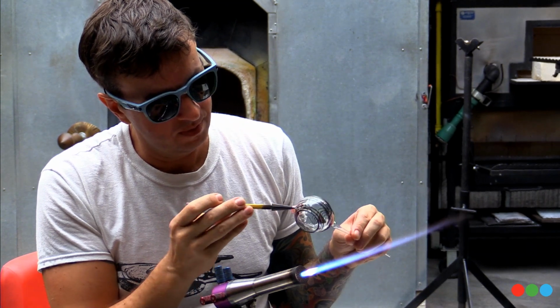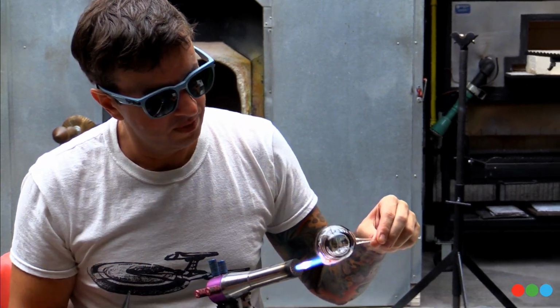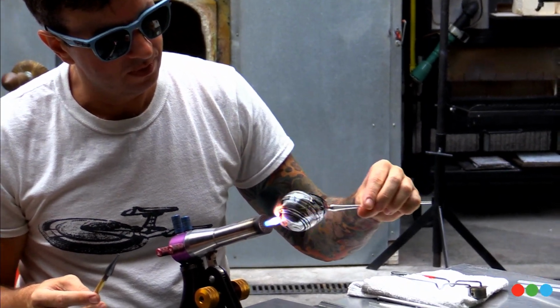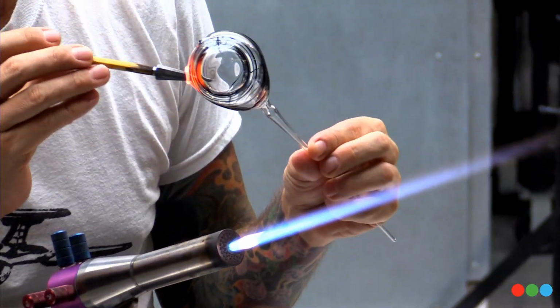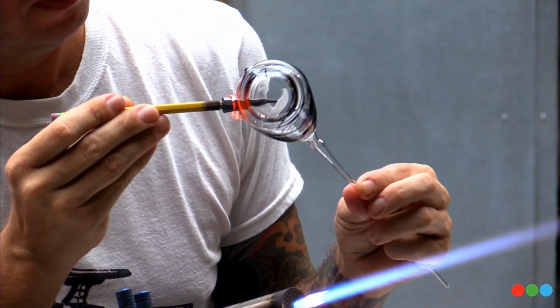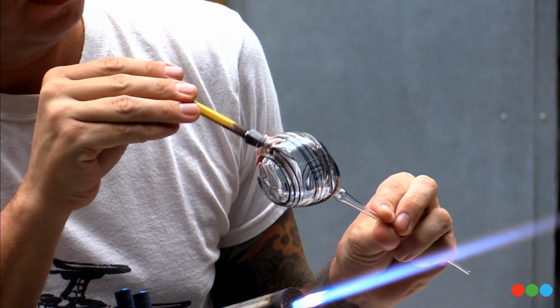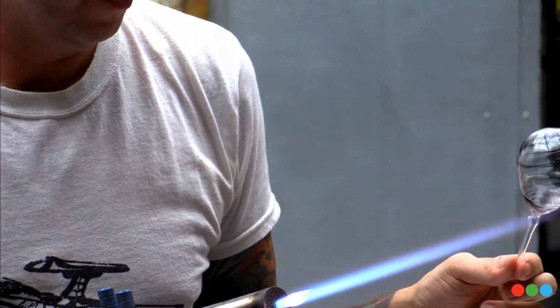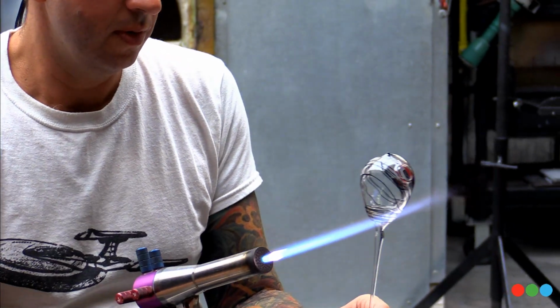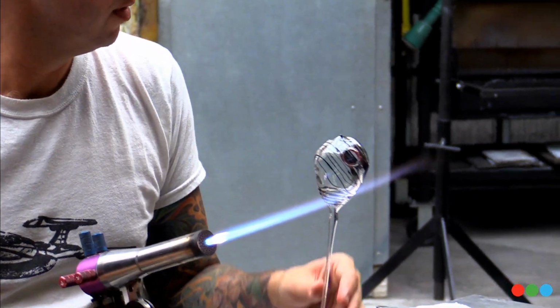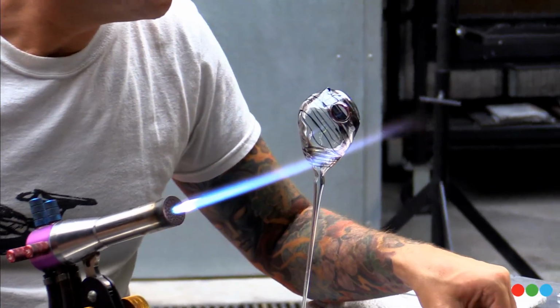It actually grows. It's not a lot, but it grows a little bit. And that's where the cracking comes in. If you heat something up too quickly, the surface is expanding, but the center, the core, is not expanding. Stress is building up and it breaks. And then the same thing happens in reverse. If you cool it off too quickly, the surface cools and shrinks, but the core doesn't. Stress builds up and it breaks.